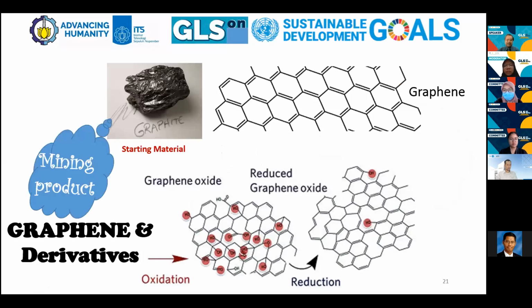Commercial graphene is currently made of graphite, which is mined as a non-renewable material. Theoretically, graphene has a perfect atomic arrangement and almost no defect here, although this is not the case in practice. Usually, if you buy graphene, it is not as perfect as this scheme because probably in some location of the graphene layer, there are many defects and also impurity.